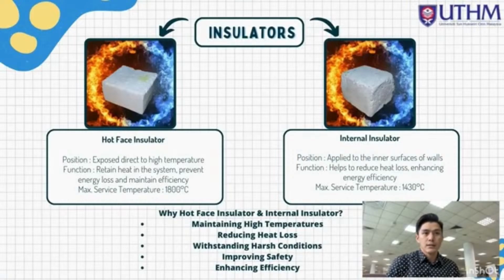As we can see from the slide, it consists of two insulators, the first one, hot face insulator, and the second one, the internal insulator. The hot face insulator is positioned exposed directly to high temperature inside the furnace. Its function is to retain heat inside the system, prevent energy loss, and maintain efficiency. The maximum service temperature can be achieved around 1800 degrees Celsius.